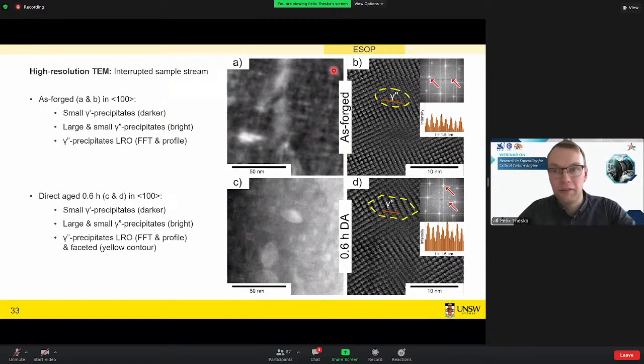The first question, I think I missed the first part of your first question. Because I saw that the structure is quite similar, right? As the as-forged and direct aging, only 0.6 hours. Is that because of the very short times? Because the G factor, if we see in the diffraction pattern in figures B and D, is also similar. Yes.